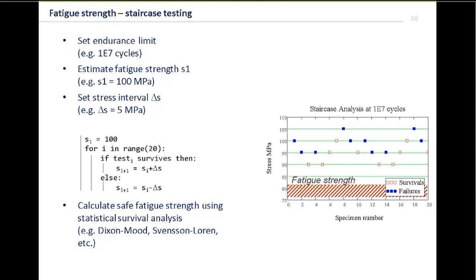We do lots of tests, almost to destruction. So let's set our first specimen in the rig, and we're going to target it for 1e7 cycles. Now, our first one here actually failed before that target. So for the next test we reduce it to just 95 megapascals, as you see in the diagram on the right. And we test it again. In this case, that new specimen also failed before it hit the 1e7 target. So now we repeat the test with another new specimen set to 90 megapascals.